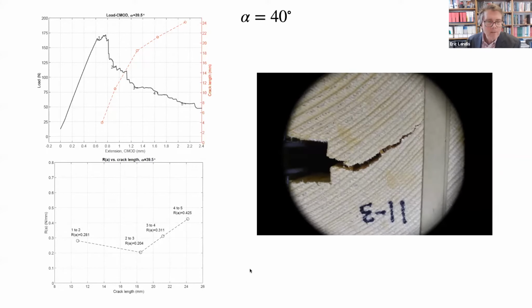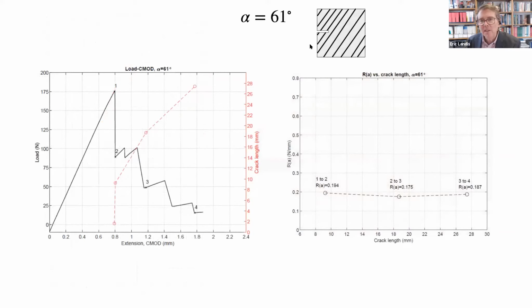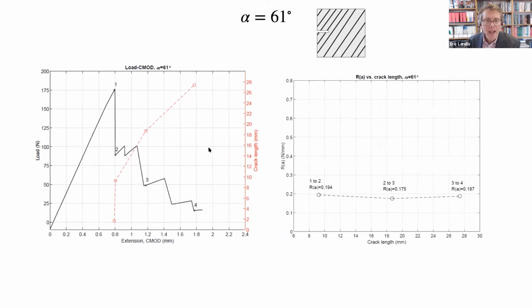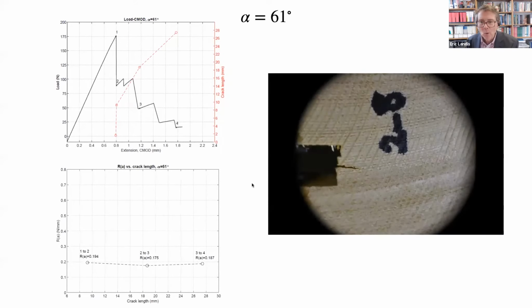Then we do have a gap, I admit, but now they go to an even steeper grain angle. And now what we see, definite regions of crack instability. Despite the fact that we have CMOD control, you can picture if a crack is going from a region of higher resistance to lower resistance, once it gets through the high resistance, it's probably going to have enough energy to propagate through.